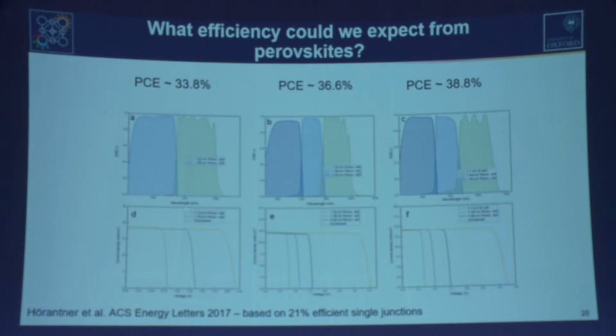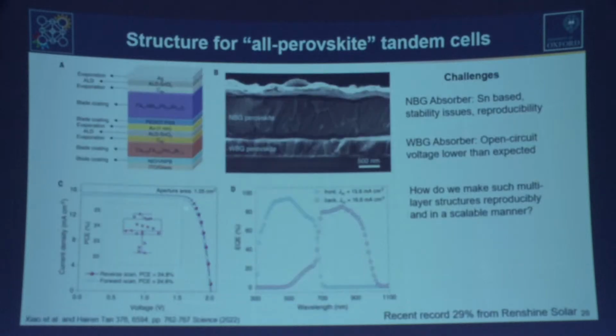These are the efficiencies we think we can practically get with today's perovskite cells if we tune their band gap, tune their composition to make the different solar cells. So we should be able to make 2-junction tandems close to 34% efficiency, and 3-junction cells somewhere between sort of 36 to 39% efficiency. These are the targets that we're aiming for.